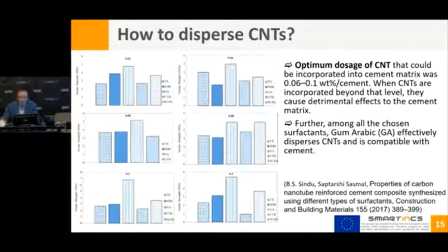Then you have here the effects of this sonication time onto the cementitious materials. They investigated different superplasticizers, so I won't at the moment detail them. We will talk about them later. They incorporated different amounts of carbon nanotubes, from 0.02 weight% up to 0.3 weight%.